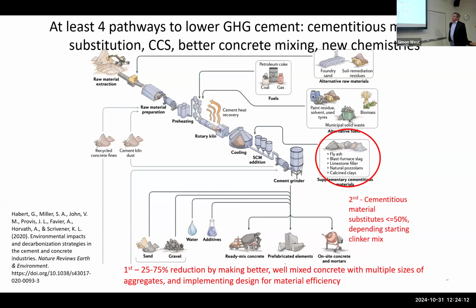The next big place that you get a lot of reductions is cementitious material substitutes. If you've got blast furnace slag, or coal fly ash up to a certain point. But then you move on to things, there's a mixture, you can use a mixture of roughly 1/3 ground limestone and 2/3 calcined clays. That can displace about half the clinker without affecting the ultimate performance of the cement, right? Using that, which costs roughly the same to make as clinker, you can knock out another half of the emissions if you're starting at 100% OPC, depending on your clinker mix. It's not as much in China because they're down at 67% clinker mix, but they can go down from 67 to 50.